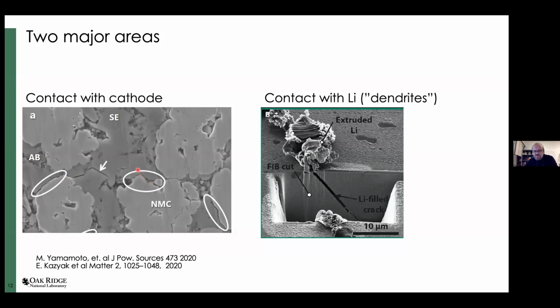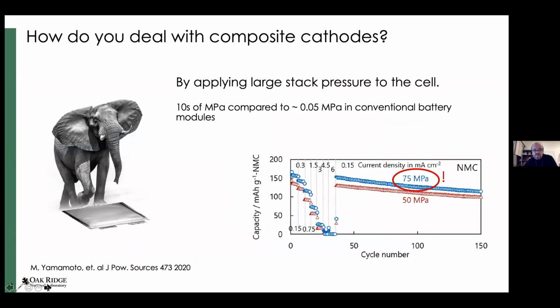So you don't have the transfer of your ionic current into the electronic current at this interface anymore. So to keep all these interfaces together, people apply very large pressure to the battery stack, just to keep everything close to each other. And just simply by jumping, this is one of the examples, from 50 megapascals to 75 megapascals, you can increase the performance of the cell. But then again, 75 megapascals is okay if your footprint is a tiny little experimental cell. If you apply that much pressure over a large pouch cell, let's say from a Ford Focus EV, for instance, that will require a lot of force, very impractical.